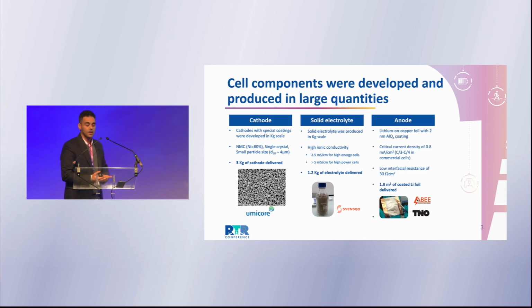So for the anode, because we are using a lithium metal anode, it is very challenging. Our partners, ABEE and TNO, were responsible for making stable coatings to apply coatings on lithium metal anode and make it stable. And we deposited a special aluminum oxide on a lithium metal anode, and we went through several iteration steps to optimize this coating, and at the end, our partners could deliver 1.8 square meter of this coating. So this is on a material level.